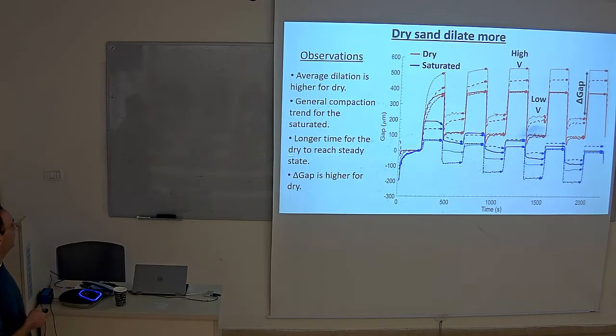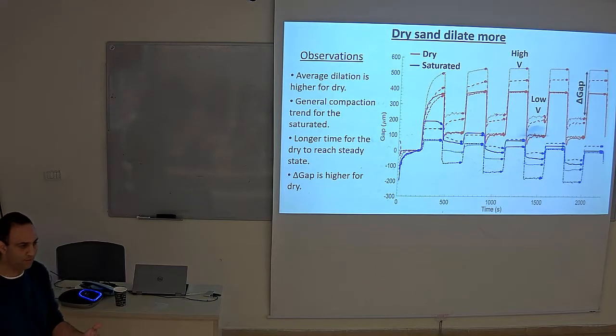Longer time for the dry to reach a steady state. So here it's taking time until it's getting a steady state, maybe here. While for the wet, it's getting very fast to a steady state, and this is also maybe caused by a little bit of change in pore pressure. And the last thing, which is the main thing I want to concentrate on, is the delta gap. It's the change from low velocity to high velocity, back and forth, and that's what defines the delta gap because of the change of the physics of the system from quasi-static to the inertial regime.